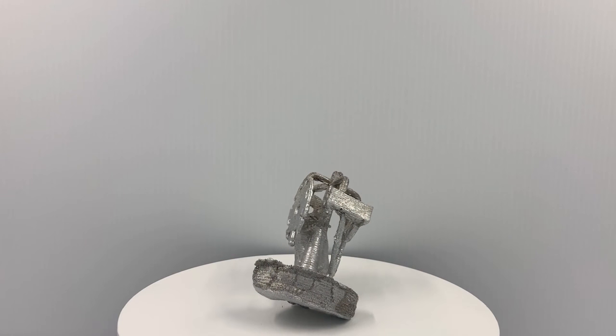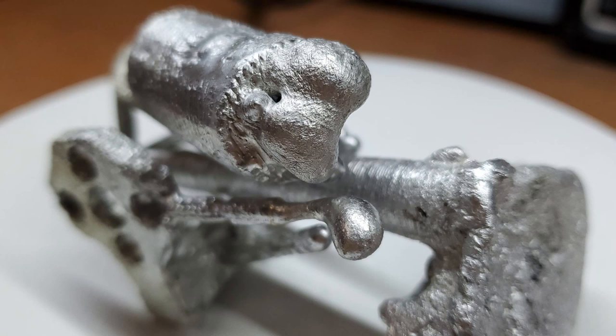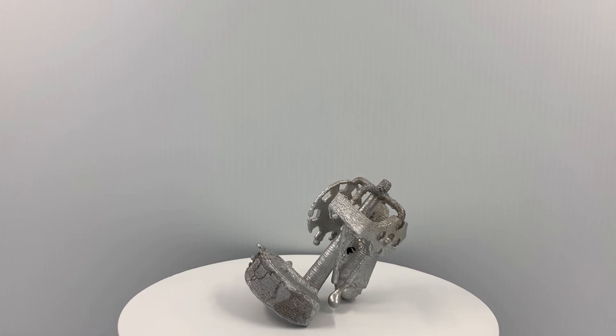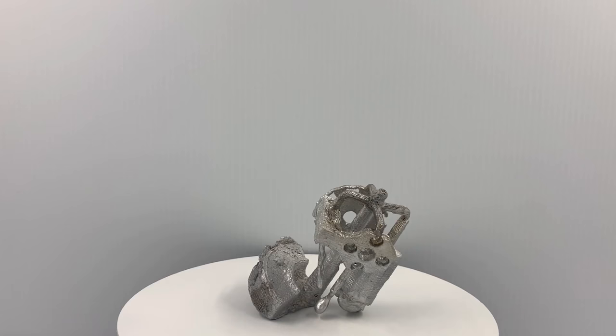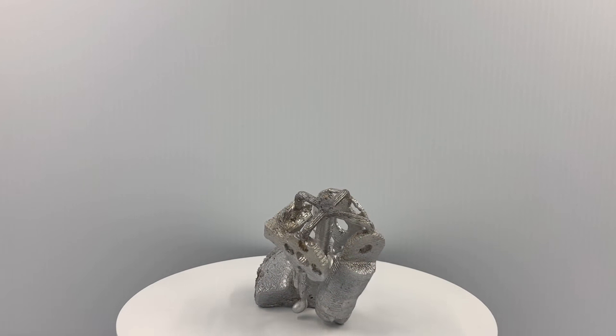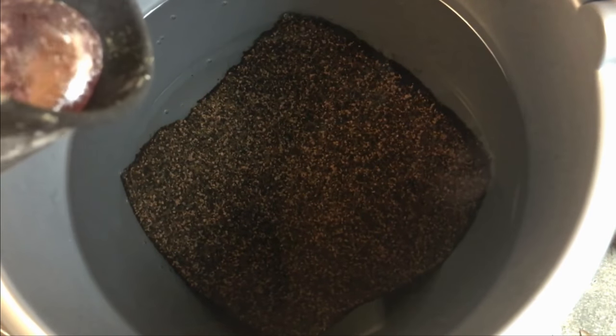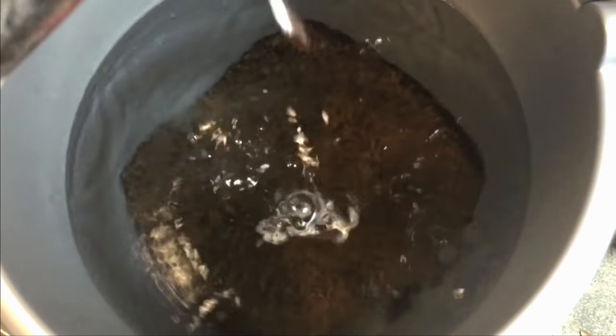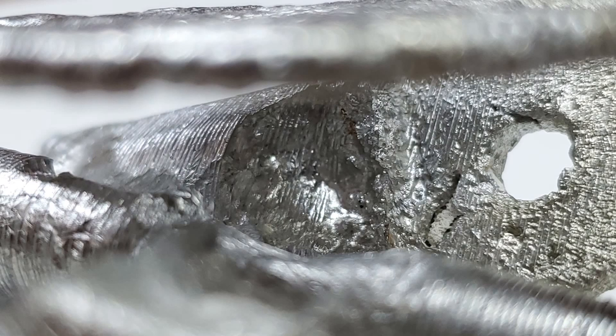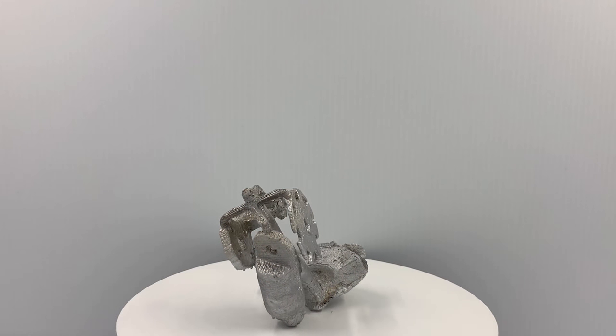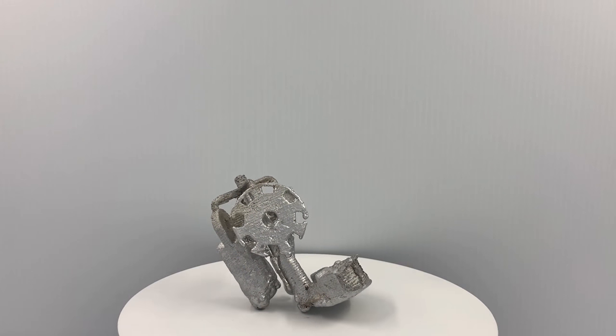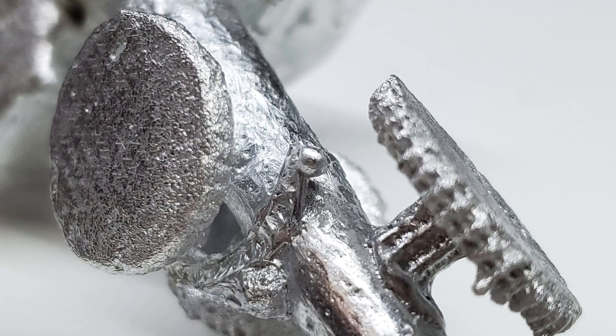Not bad. If you look closely at some of these rounded masses of aluminum it looks like some of the aluminum drained out when I drenched the plaster in water. The aluminum looks far too smooth to have been formed against plaster. Water on the other hand would cool the aluminum into smooth rounded shapes. As proof of this I put together this very scientific test. It also appears that the printer lines are still incorporated into those recessed areas. Both of these defects must be caused by drenching the aluminum filled mold in water before the aluminum solidifies. If we look back at previous tries we can see these same defects.